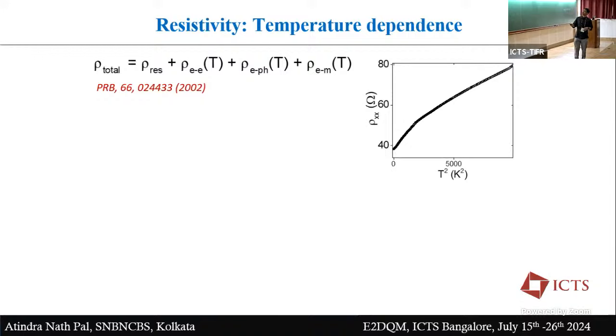You have all different types of components. One is the residual component. Then you can have the electron-electron interaction term, which should go as T square. And then you can also have an electron-phonon term, which is typically proportional to temperature. And you can also have an electron-magnon term, and electron-magnon scattering is proportional to T square. So then we try to fit the data.